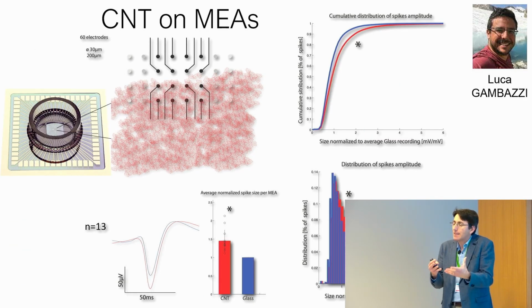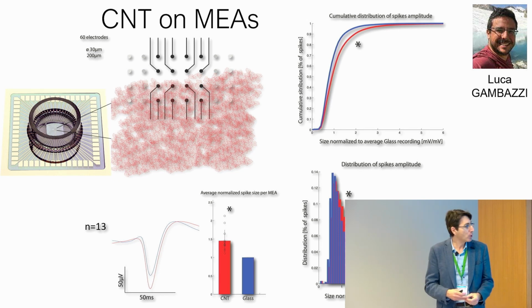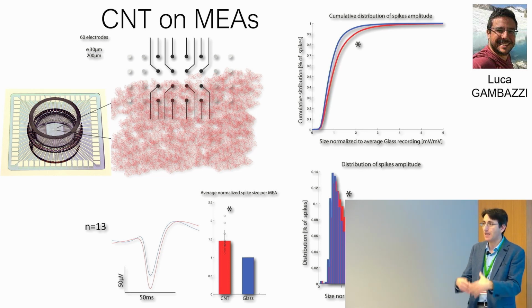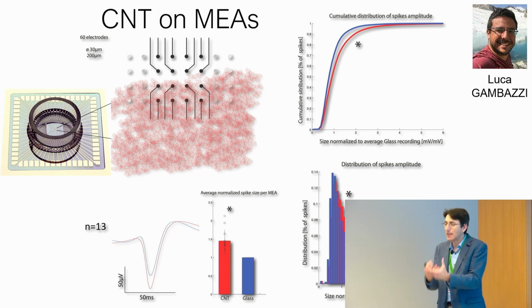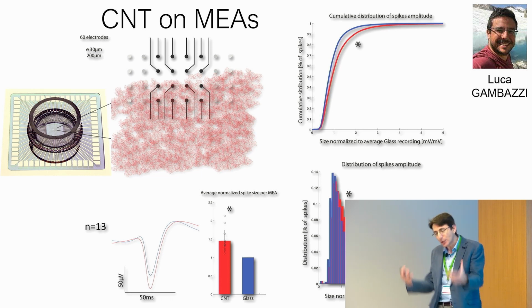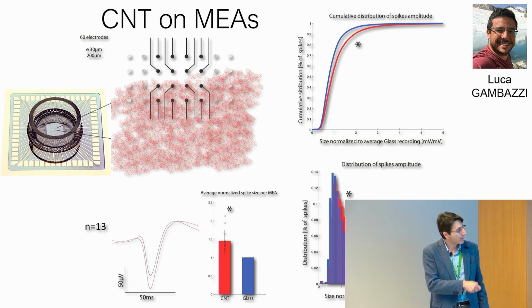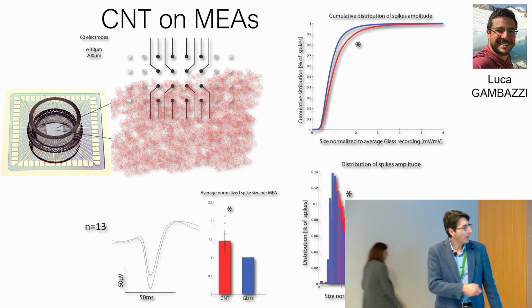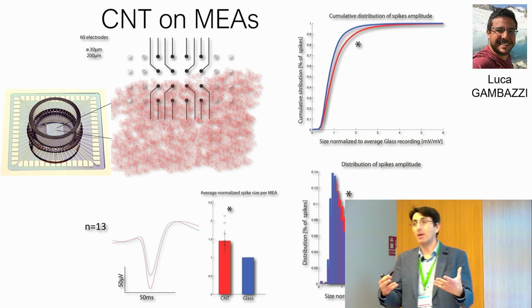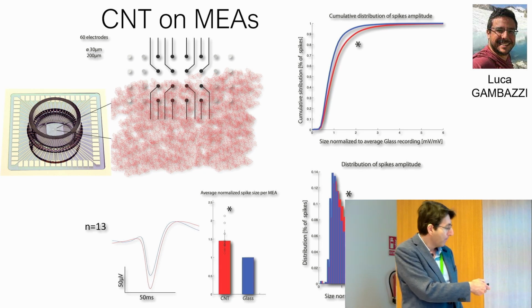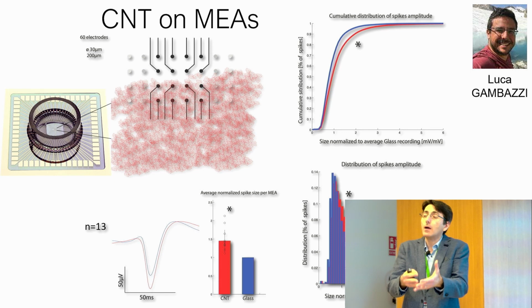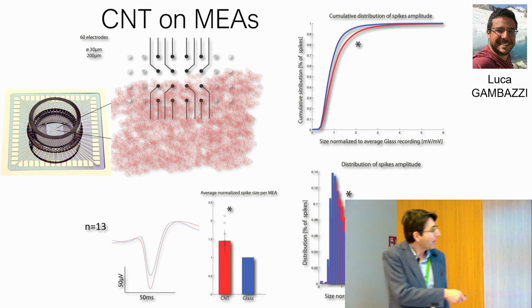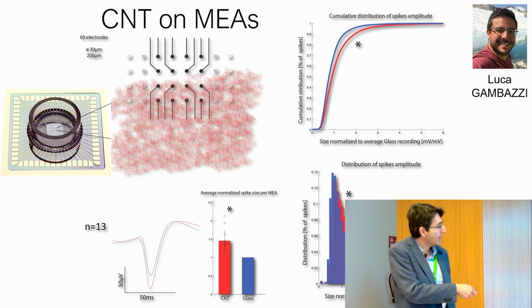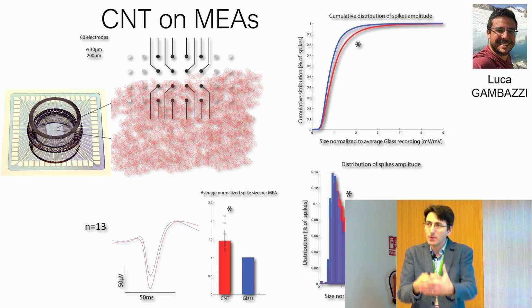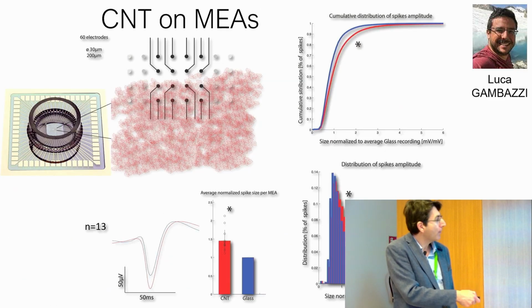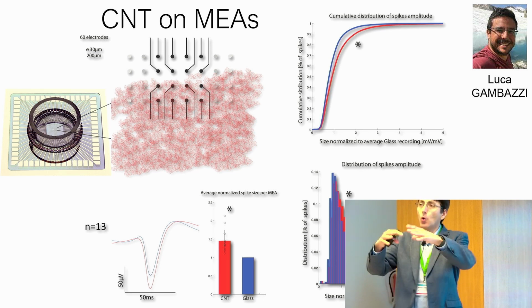So we were intrigued by this, and we wanted to study it in a more systematic way. Once more, we resorted to going in vitro because of the ease of physicochemical accessibility and control, instead of in vivo, where conditions and the tissue reaction are a problem. We considered substrate-integrated microelectrode arrays, very standard devices made on glass substrate and obtained by standard microphotolithography since the 1970s. These devices are commercial. We cultured cortical as well as hippocampal neurons from the rat. Just before plating the cells, we deposited carbon nanotube meshworks in such a way that only half of the array, this sort of fakir bed, was coated.